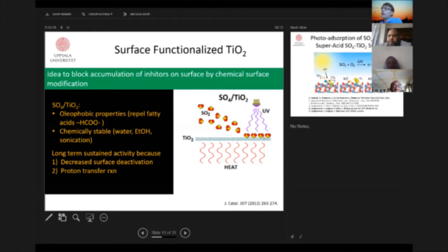And as you know, when you have a low pH surface, you have quite nice properties. Of course, having this low pH, you have this proton-mediated reaction transfer mechanism occurring. It has some really interesting oleophobic properties, so that it is simply not possible to stick grease on the surface. And it has properties for long-term sustained activity, because it decreases surface deactivation, because this provides a proton reaction channel to mediate surface reaction, as I will show in the next slide. And on top of that, it happens that these bind on the sites which are prone to deactivation. So it's a balance. You lose some of the initial activity because you block some sites, but you gain the sustained activity.